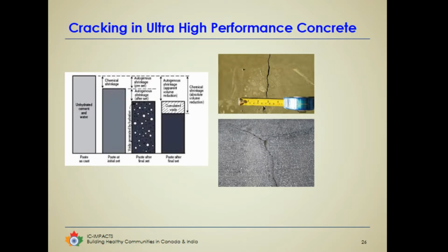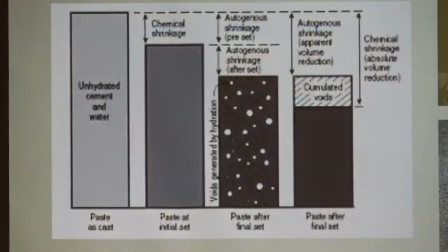And this particular problem comes from self-desiccation. Because in order to increase the strength you have reduced the water content, what you end up having is basically a material which has a much greater desiccation, much greater reduction in relative humidity inside. And the moment there is a drop in the humidity, you end up having cracking in the system because the material is actually now trying to shrink. So this is a very large problem with ultra-high performance concrete.